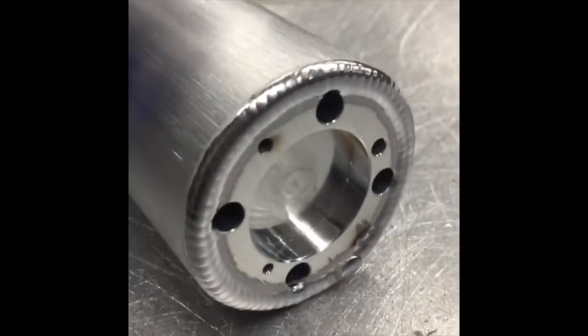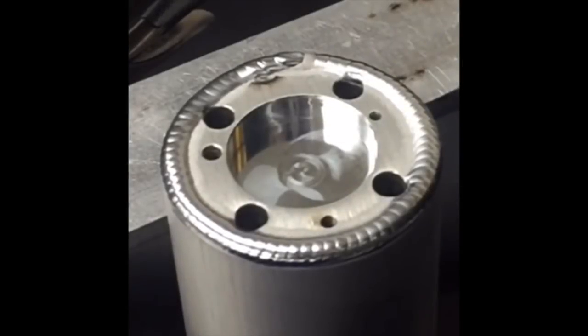So since those two relate as far as needing a really stable arc on those real small diameter stainless parts, let's talk about that just a little bit. Let's talk about the electrode prep. You posted kind of recently some different arc plumes coming off of a 25 degree, a 35 degree, and a 45 degree prep. I know the textbooks show you something very similar to this on penetration profiles, but how does that relate to those little thin wall stainless parts that you do?